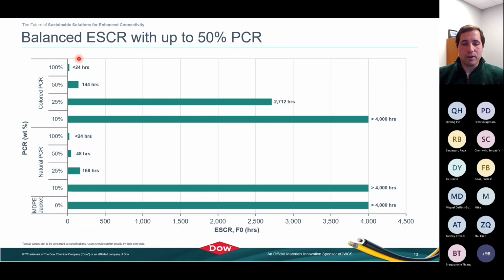So along with the mechanical properties, another critical thing that we looked at was the environmental stress crack resistance. When you consider the colored and the natural PCRs against the control, where the control can last greater than 4,000 hours, particularly at the higher percentages of PCR you have much lower stress crack resistance, so less than 24 hours for the pure PCR. But as you incorporate around 25 to 50%, depending on the source, you can start to get better performance, and it really would depend on the specification or targets for a given application.